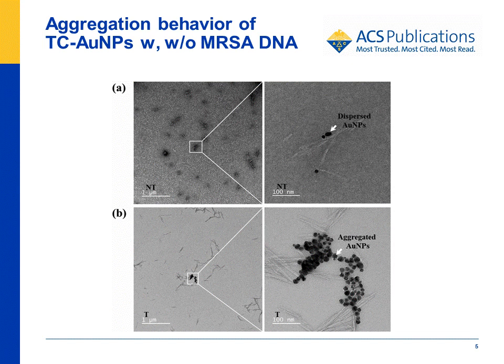The agglomeration behavior of the ssDNA incorporated TC-AuNPs with or without target DNA in the presence of 8 millimole NaCl solution was evaluated by the ultra-high resolution TEM images. The non-target media showed the well-dispersed nature of the TC-AuNPs. However, agglomeration of the TC-AuNPs was observed in the target media.